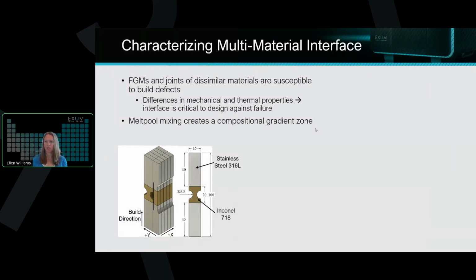This was a collaboration with Ohio State, where what they have done is strengthened the notch of a tensile bar with an Inconel 718 and then use stainless steel 316L in the tensile bar's grips in order to use an alloy that has preferred mechanical properties for the area where you need the tensile bar to be strong. But of course, anytime that we are changing material types, and when we're going through this printing process of changing material between a layer, we are going to have differences in mechanical properties and potentially some defects or weaknesses at that interface. So it's really important to understand what sort of compositional gradient we're getting right at that interface, and determine how we might want to improve that going forward.